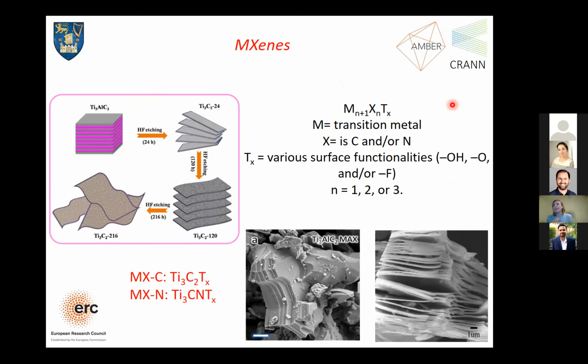And here I introduce a different class of 2D systems that actually Christina loves as well. We share the love for this class of materials. For those of you who have not come across MXenes or don't work with MXenes, this is a wide family of materials. The ones I'm going to focus on are mainly titanium carbides and carbonitrides, so Ti3C2 and titanium carbonitride. These are different types of 2D systems, in fact, because they start from MAX phases, which are layered but not held together by van der Waals forces as any other 2D system I showed you before. In this case, we etch away the middle layers, and what we end up with is a sort of accordion type of structure after we do some aggressive etching of the initial precursor, the MAX phase.